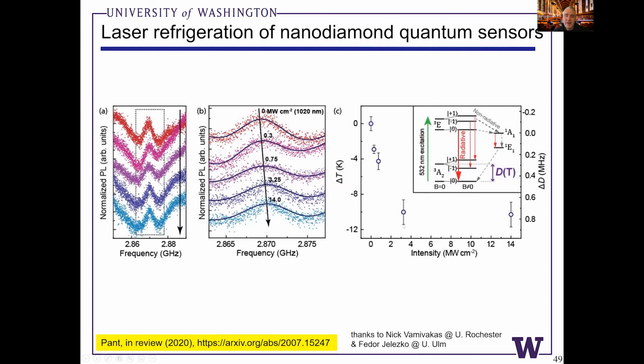And once we saturate the absorption of the ytterbium, the cooling stops. But we can control the temperature. We can effectively compensate for any intrinsic heating of the diamonds, bringing it back to a 0 Kelvin heating situation, and even cool the materials to on the order of 10 degrees Kelvin below room temperature. And these measurements were in air.